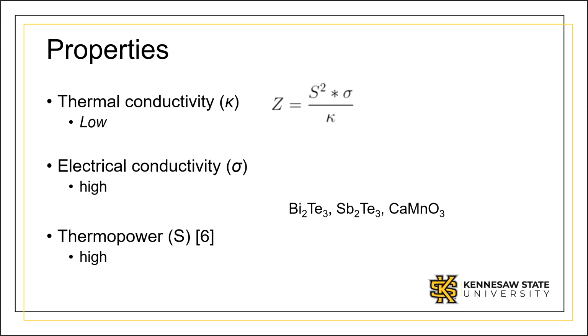Thermal conductivity measurements on thermoelectric materials can easily be made using Hot Disk TPS instruments. These three properties can be used to calculate the figure of merit, which is an overall indicator of the quality of a thermoelectric material, in the equation shown, where S is thermopower or Seebeck coefficient, sigma is electrical conductivity, T is absolute temperature, and K is thermal conductivity.